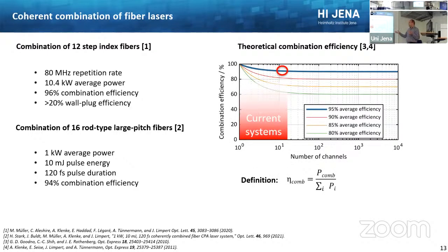But the question is, of course, at this point, how far can we go? How many channels can we combine? Theoretically, quite a lot. On the right side, the combination efficiency, meaning the power you get out of these systems over the total power of all the amplifiers, is shown. And maybe contrary to what you expect, this total efficiency does not drop with the number of channels, but follows these curves that you can see here. We are operating more on this blue curve. So even if you had 100 channels or 1,000 channels, at least theoretically, you should be able to build a system with high efficiency.